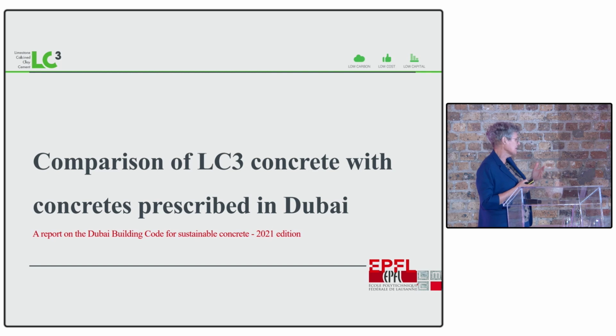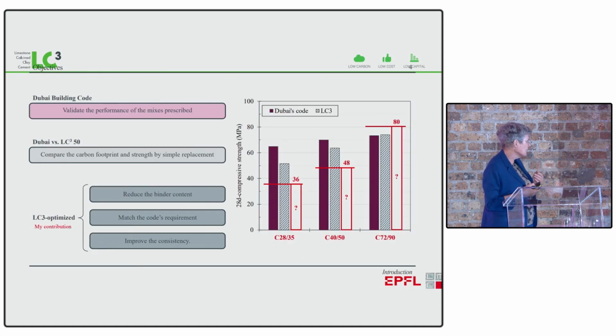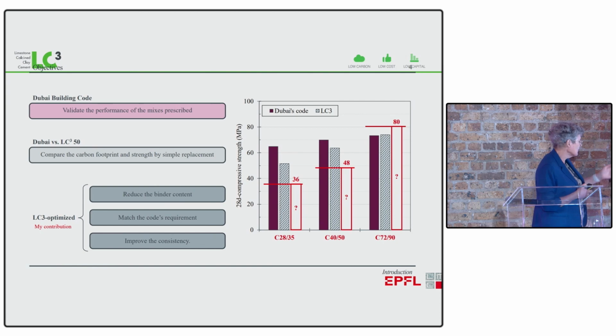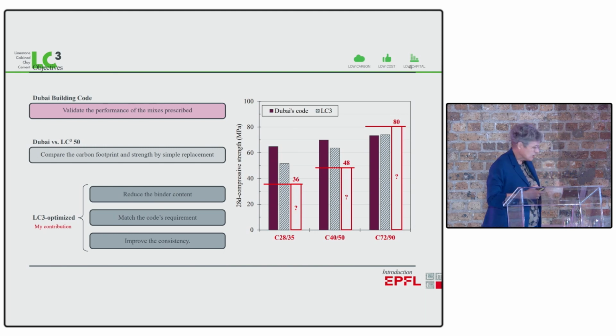So in Dubai, because they have a lot of durability issues, they're prescribing concretes containing fairly high amounts of slag and silica fume. This then shows what happens when you take out the binder they put in and you substitute it with LC3. Well, you can actually see that 2 out of these 3 concretes, the 35 MPa and the 50 MPa, are actually massively over-designed. They have much higher strength than needed, while the C90 concrete is under-designed.